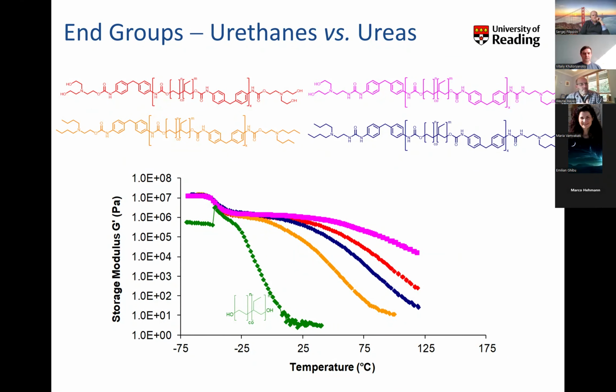And these materials are similar to those that have been reported by other groups such as Meijer and Zimmerman, which are excellent examples, but their systems have highly pre-organized, extremely strongly hydrogen bonding end groups with dimerization constants for the association of the end groups up to 10 to the 7 reciprocal molar. Whereas these systems here are far weaker in nature. And so what we believe is happening with our systems is, rather than having very distinct hydrogen bonded assemblies, we're creating very loosely associating domains of our polar end groups where there are lots and lots of different hydrogen bonding combinations occurring in the polar end groups.